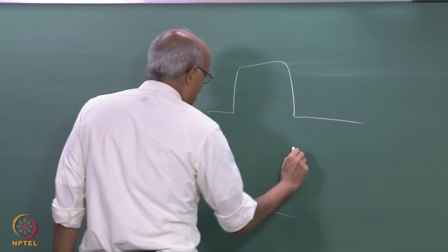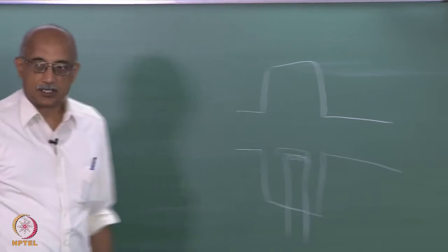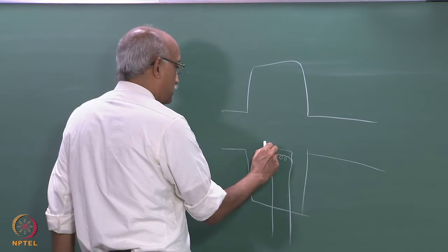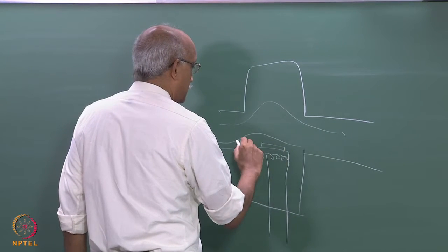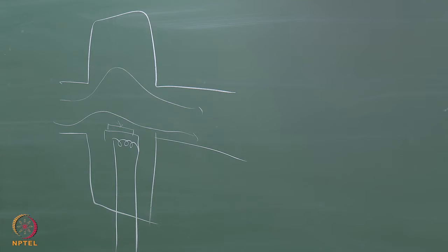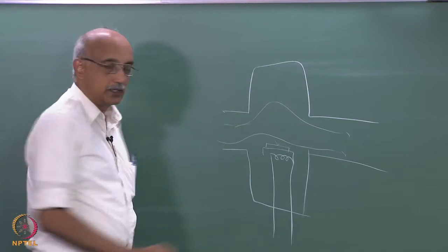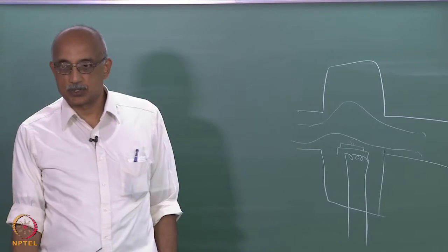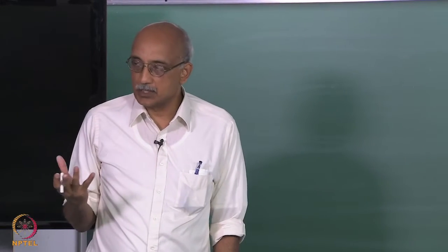So again, what we are really looking at is an extension of a bell jar. In the normal CVD reactor, you would have a substrate to which you are providing some source of energy. And so you have your wafer sitting here, and the gases are flowing in some fashion over this reactor, and the deposition process takes place over here. So the reactants are preheated before they enter the reactor, and typically you use a cold wall configuration to ensure that the deposition only happens on the substrate. So this is one variant of design of a CVD reactor.